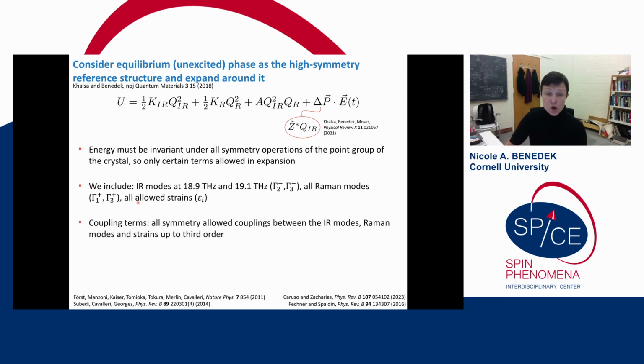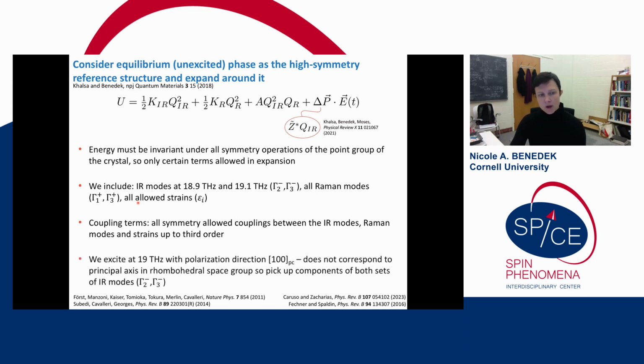We include all symmetry allowed couplings between the IR modes, the Raman modes, and the strains up to third order. And we excite at 19 terahertz with 200 femtosecond pulses, and we pick up components of both sets of these IR active modes.